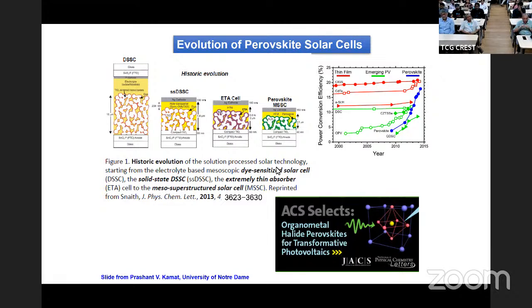This is what Michael Gratzel had introduced as a competitor to the silicon photovoltaic technology, called the dye-sensitized solar cell, which said that about a 10 micron thick device is good enough. And systematically, this technology was evolving into extremely thin cells. But this active material that I just now introduced, the perovskite-based system, you can have sub-micron thickness, 0.5, 0.2 micron is good enough to absorb all the photons. So basically, the material cost goes down, your mechanical structure becomes lighter. So there are an enormous amount of good things about it.